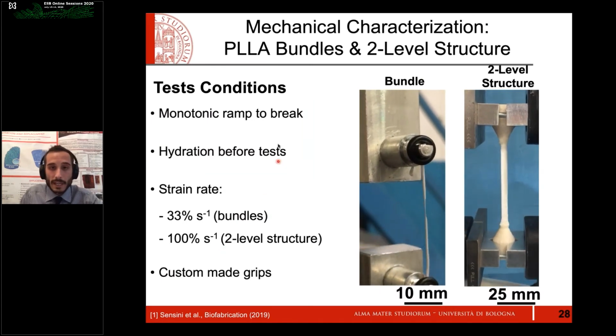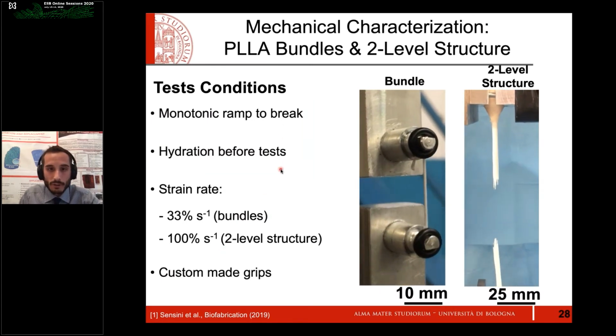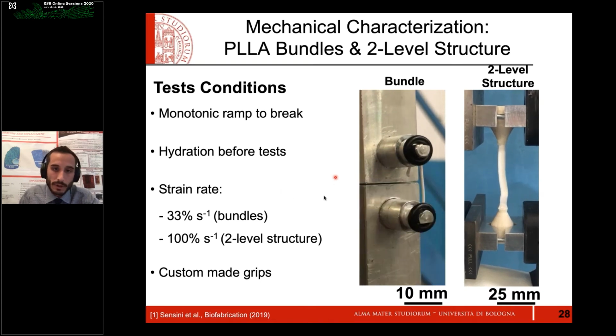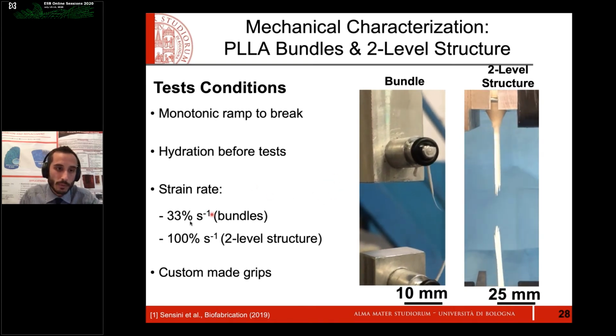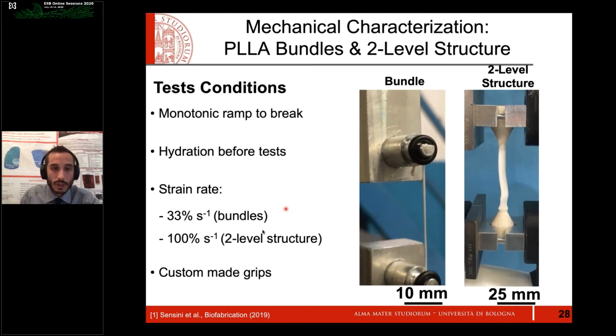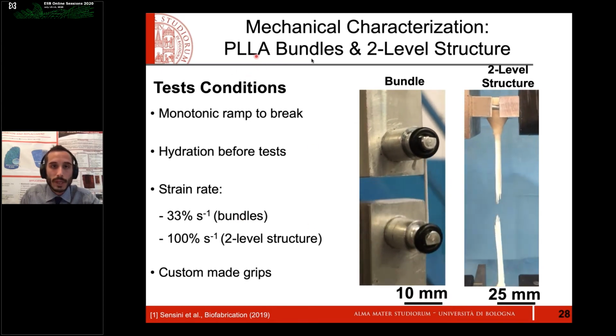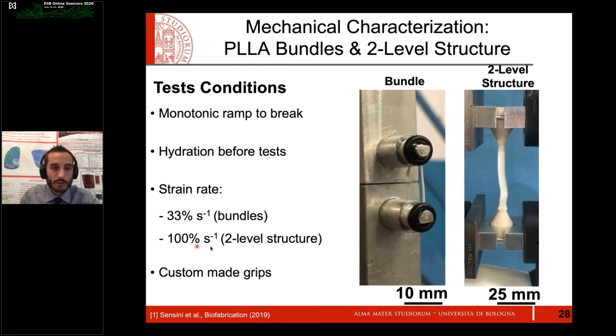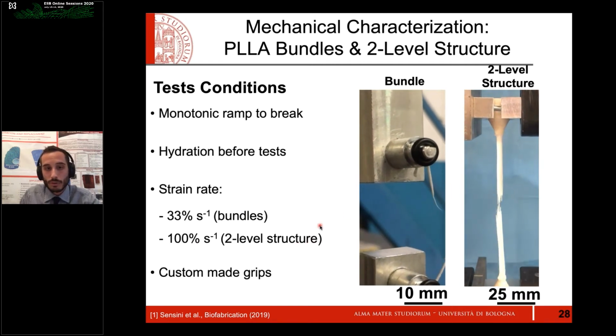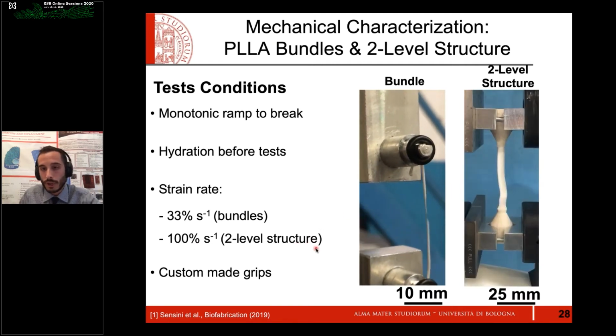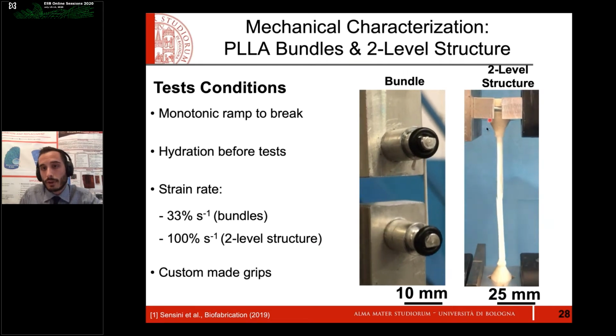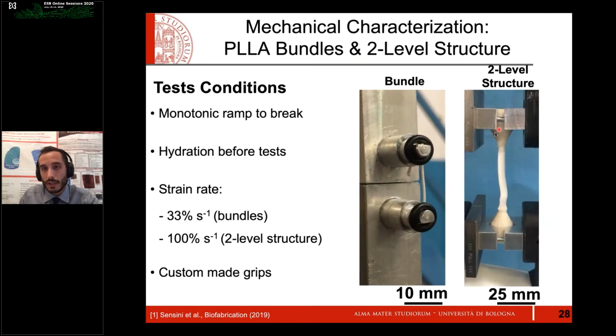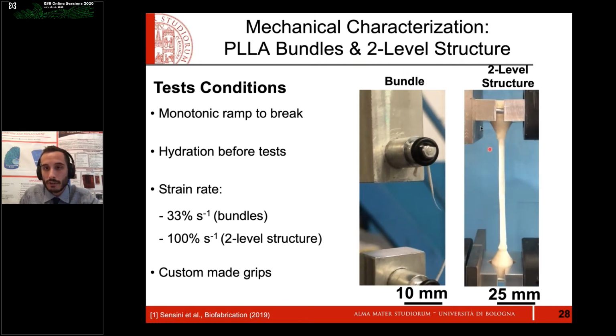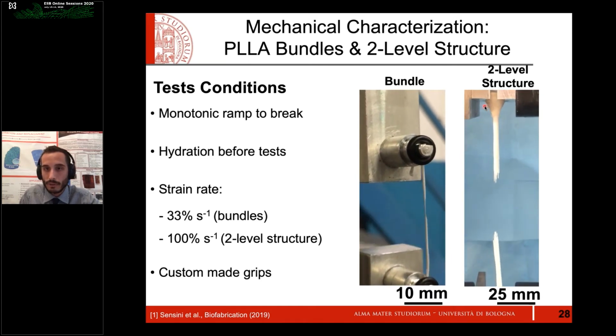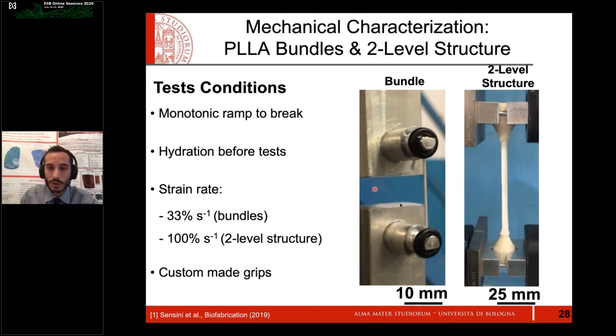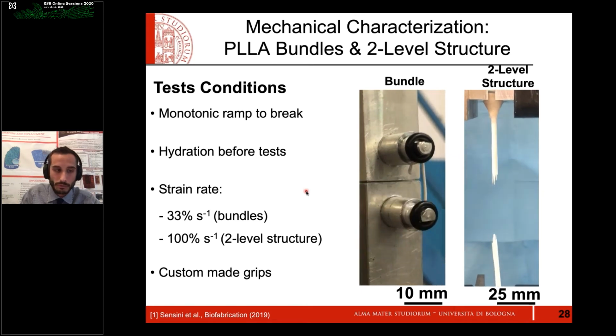We tested also the mechanical properties of the different hierarchical structures with a tensile test, comparing them with single bundles, using for the PLA two-level structure a 100% strain rate, to reproduce a worst-case failure scenario. For the hierarchical structure in PLA, we designed cemented ends to better fix them in the testing machine and reduce stress concentration, as you can see from these slow-motion videos.